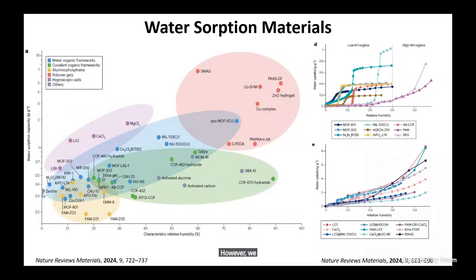This graph represents the different materials and how much water they can absorb at different relative humidities. We have that hydrogels are the materials that can absorb up to 7 times their weight in water, but they require high relative humidity. However, we have materials like zeolites, which absorb water at almost no relative humidity. As soon as there's some water in the environment, it goes to the zeolite. But desorbing from the zeolites requires a lot of energy. However, we have this blue area here, which are the metal organic frameworks, or this one also, which are the covalent organic frameworks. These materials cover the whole range of humidities, and they require less energy in order to desorb.